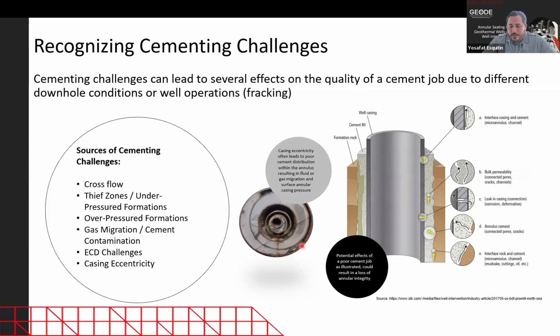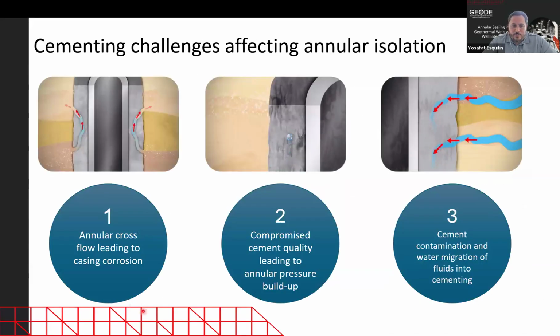So these challenges often lead to annular crossflow from this cement being challenged by the fluid placement and having those channels. And this annular crossflow, in some cases and in geothermal wells, can very often be seen to lead to casing corrosion and casing challenges. So it's very critical that crossflow is stopped and maintained at the reservoir section.